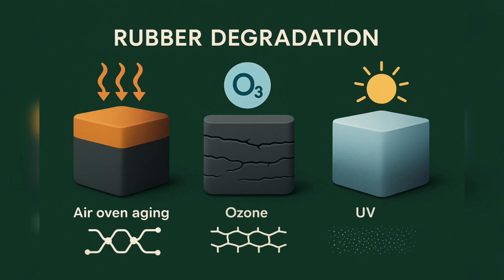If ozone makes cracks, UV makes dust, a faded, powdery surface as the polymer degrades and fillers or pigments migrate to the top. Now, each of these aging methods simulates a different mechanism, which is why their failures look so different. Air oven aging causes oxidation. Long chains break, the network becomes tighter, and the rubber gets harder and less elastic.